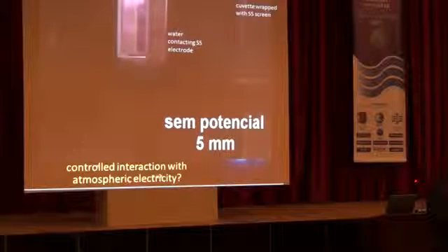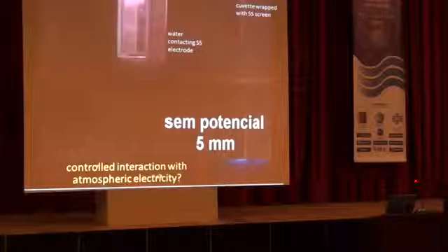And the idea that has been around all the time is that as you increase humidity, you absorb water. That increases the surface conductivity, which helps charge to be dissipated. And that's true. Nothing against this. It also contributes. But if you look at data comparing surface conductivity and rate of charge dissipation, you measure both, then you see that there is something missing.